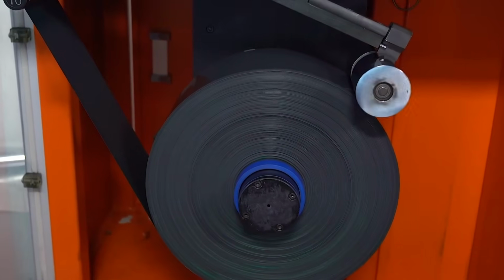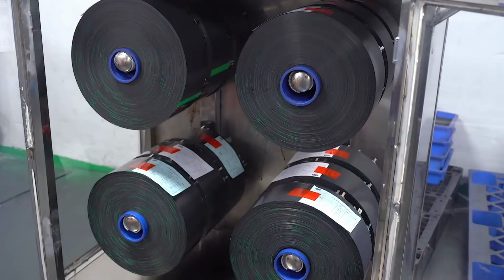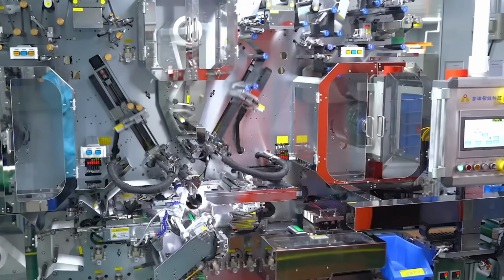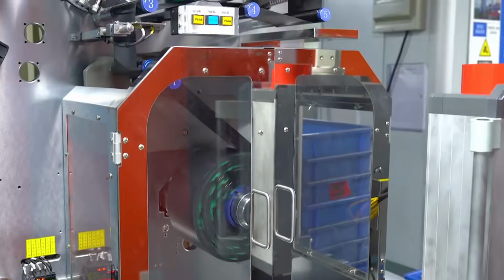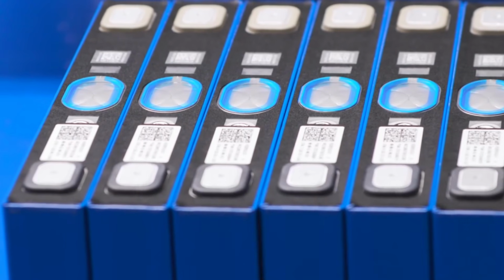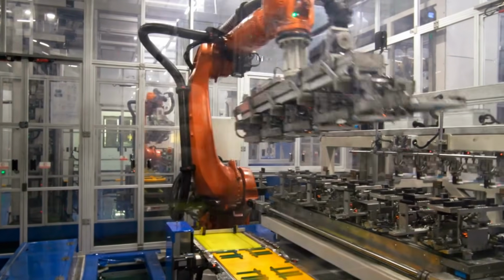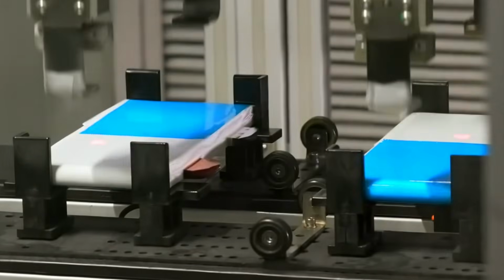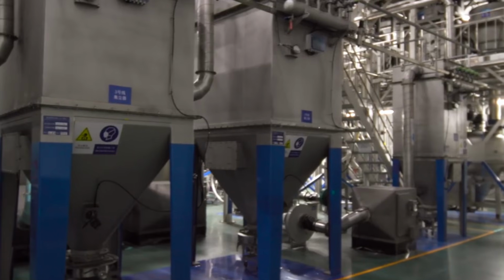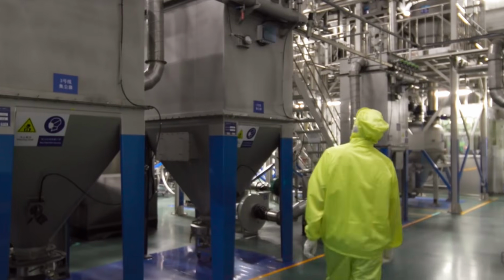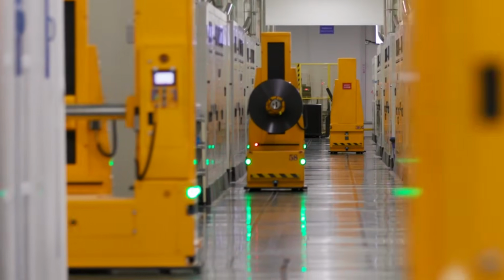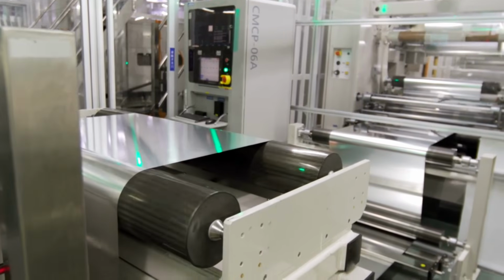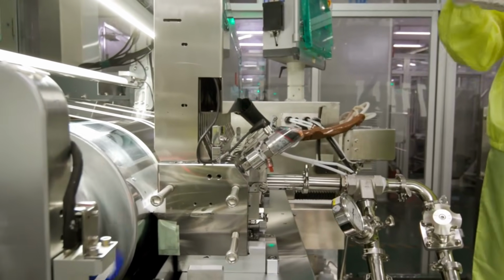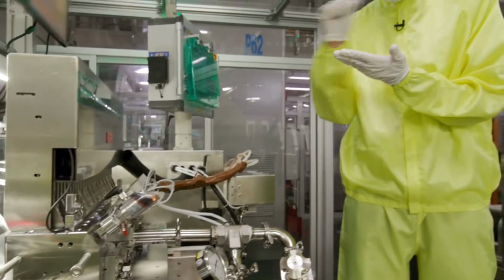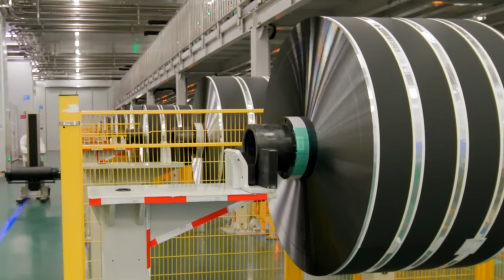After assembly, every cell gets filled with electrolyte, sealed, and then goes through formation. Formation is the first charge and discharge cycle, and it's where the battery essentially wakes up. A protective layer called the solid electrolyte interface forms on the anode surface during this step, and that layer is critical to how long the battery will last and how safely it will operate. Formation used to take days per batch. Factories have cut that time dramatically through better understanding of the electrochemistry and by designing formation equipment that recaptures the energy discharged during the process and feeds it back into the grid instead of wasting it as heat.